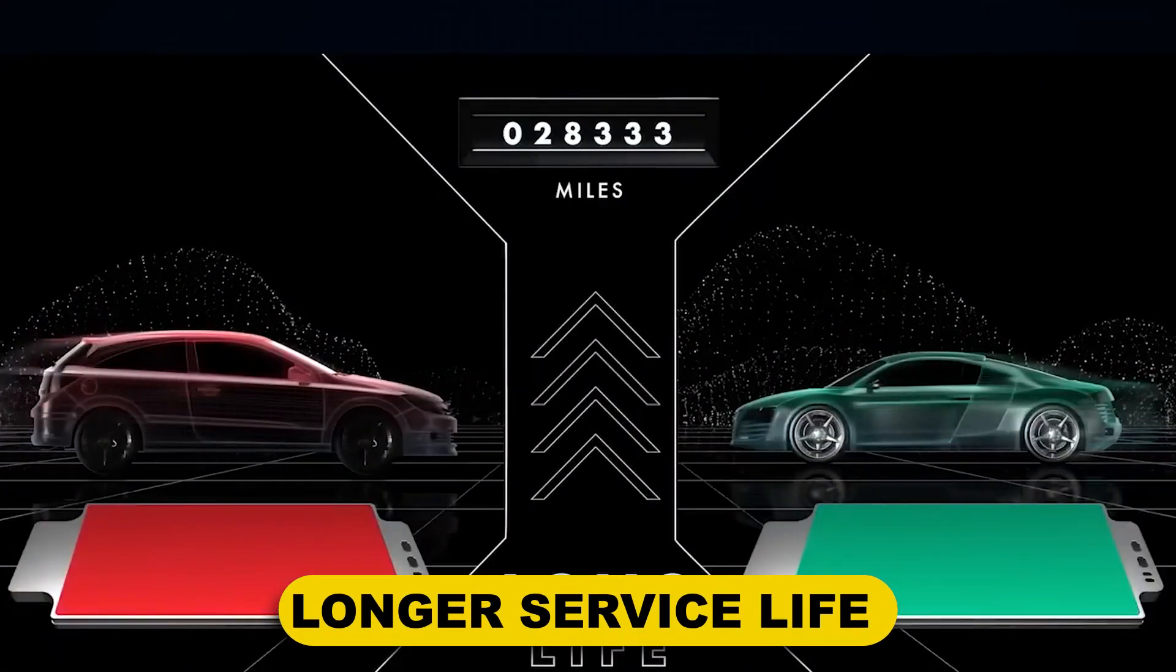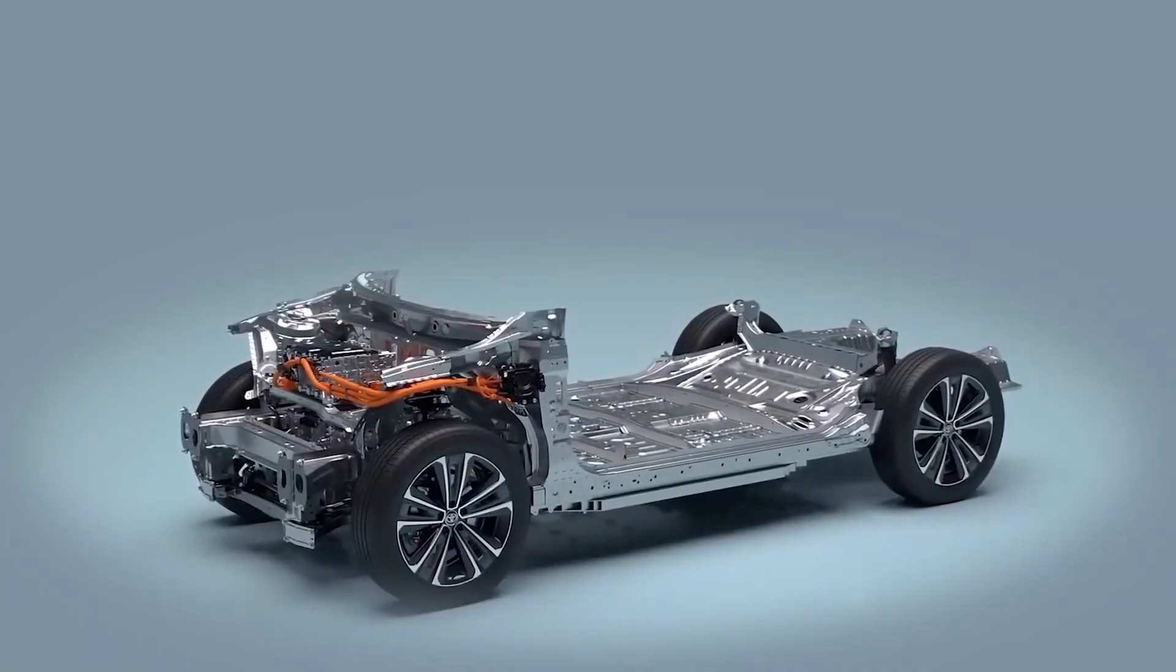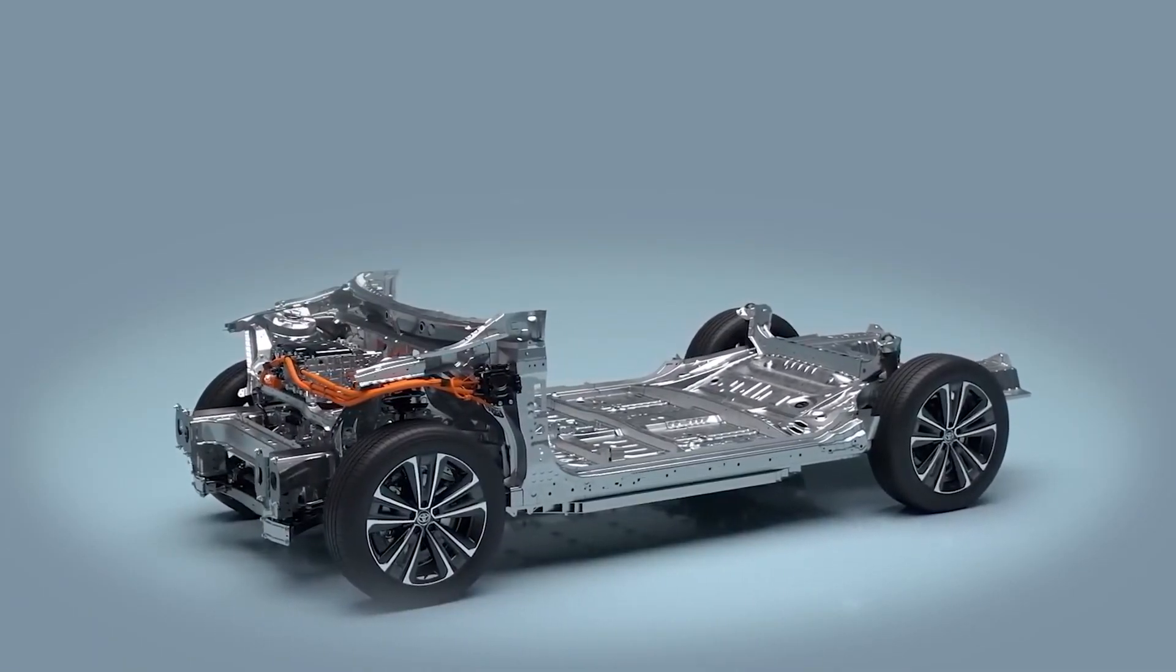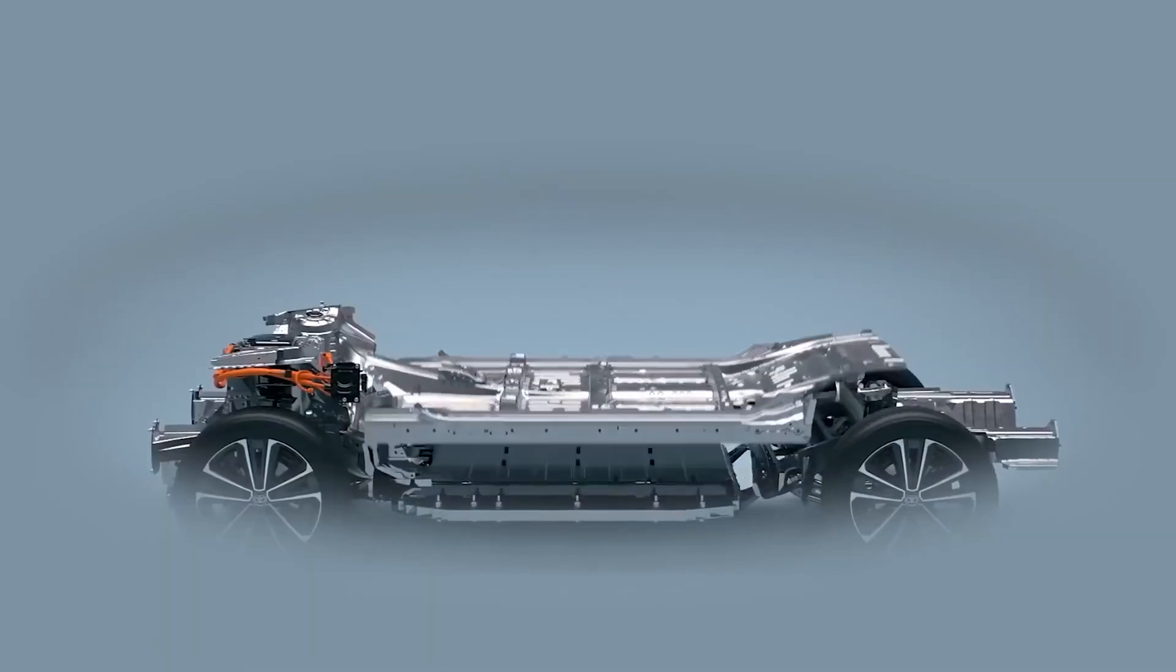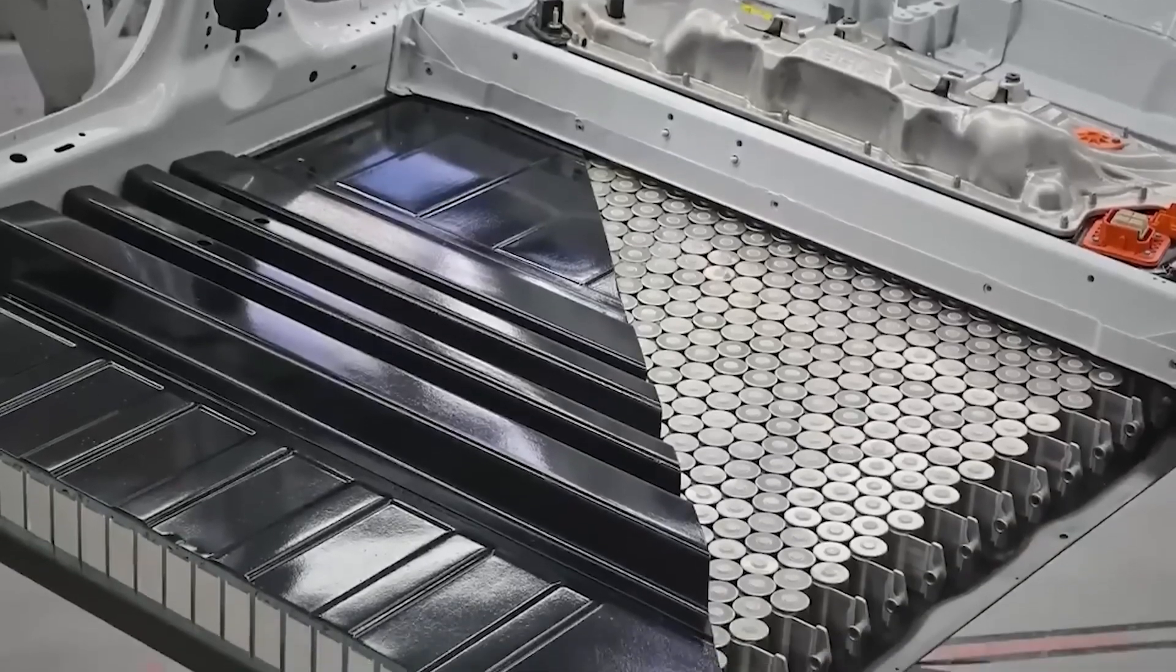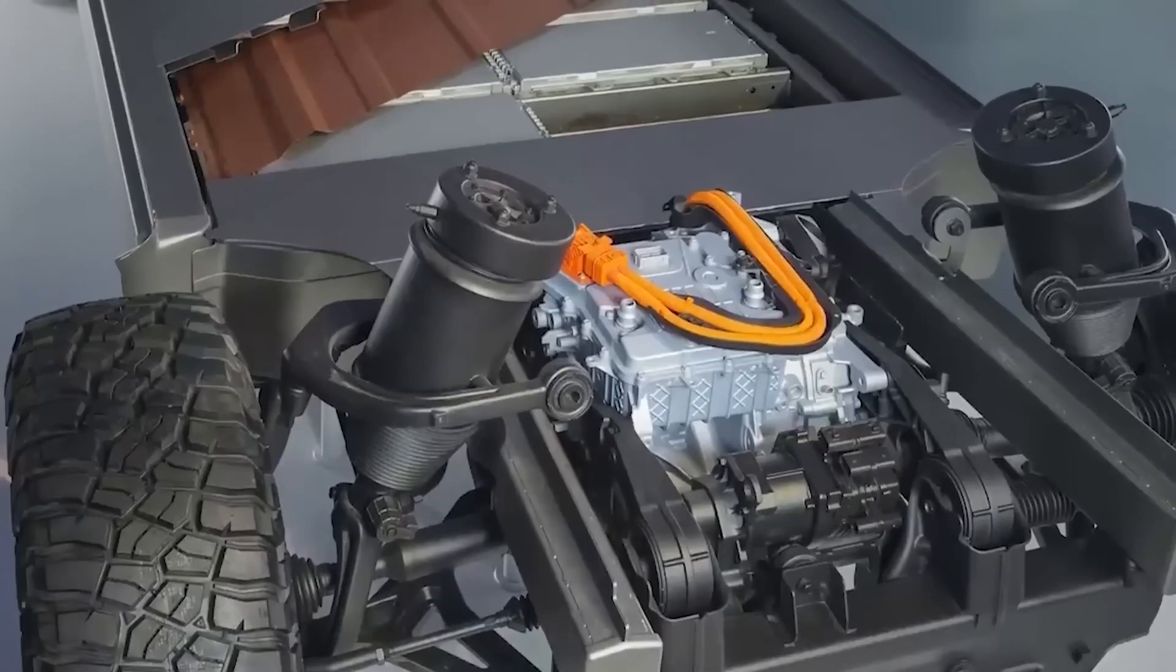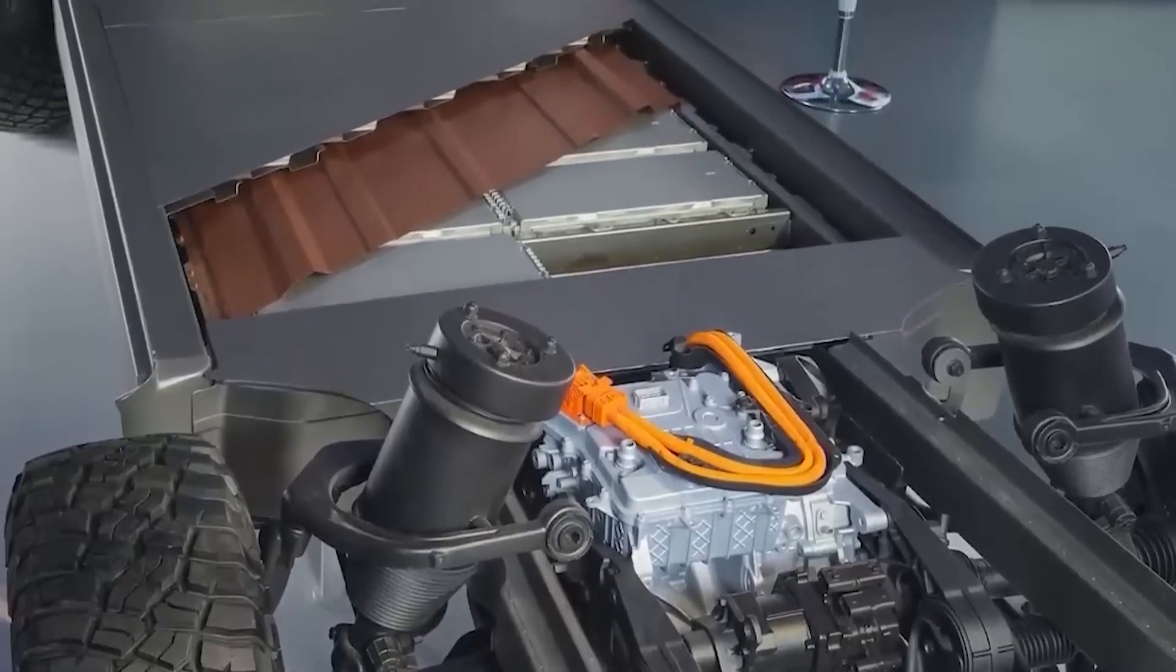Longer service life. Currently, the semi-solid battery is cycled 2,000 times at room temperature, and the capacity retention rate is greater than 85%, according to the data that is accessible. The ordinary liquid battery undergoes 1,200 cycles under the same conditions, but only around 80% of its capacity is retained.